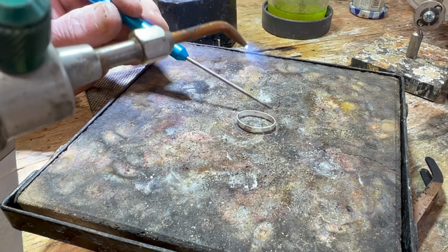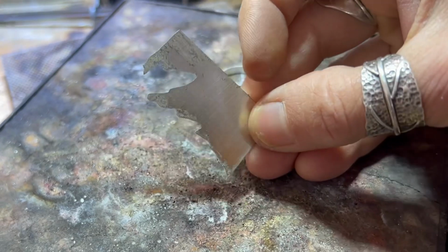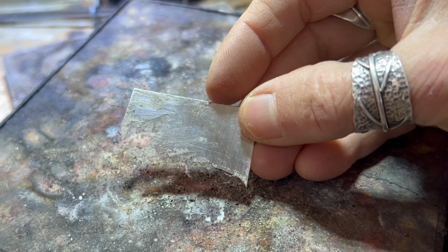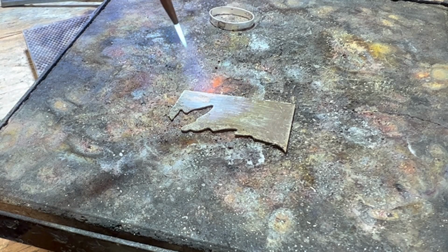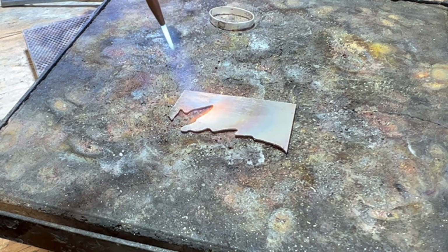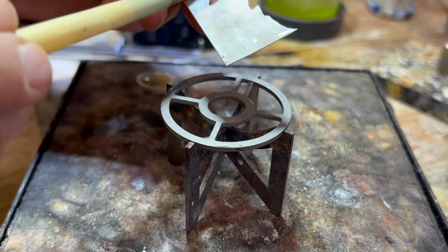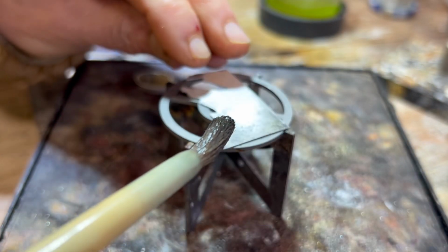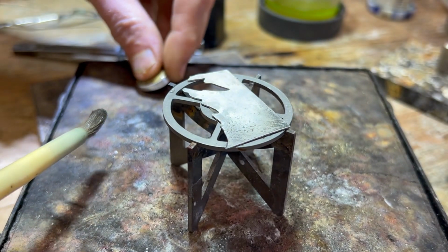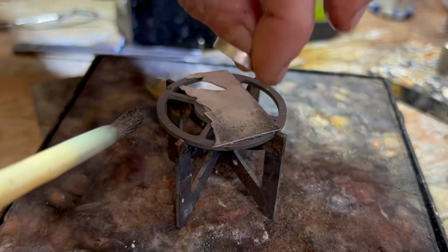In this next part, I'm going to talk about the colors of the silver as you're soldering. When silver comes out of the box, or if it's just been sitting around, I consider it gray. It's dirty, it's not porous. So you'll want to anneal it. Use a soft flame and heat the silver until after you pull away, it's black. After you have annealed and put it in the pickle, it's white, clean, porous. You'll want to flux it, and then you'll take your bezel wire and flux that and put it on the back plate.